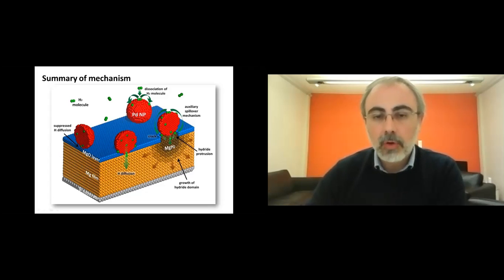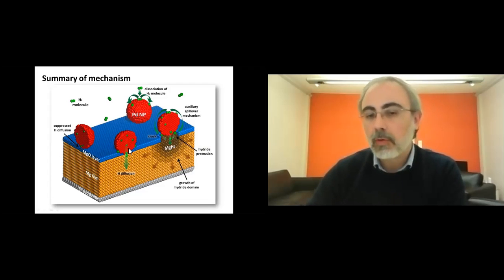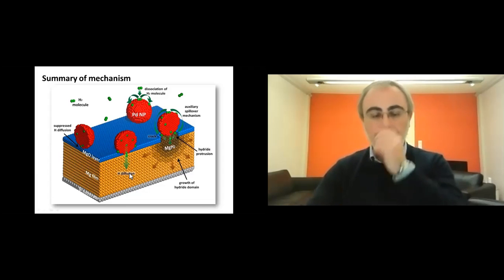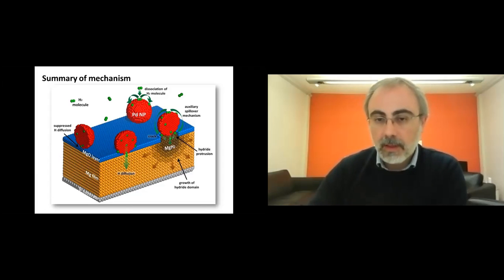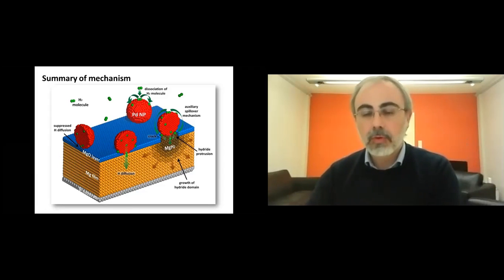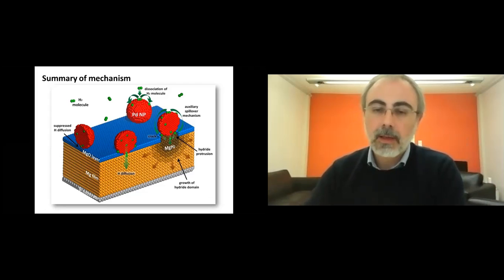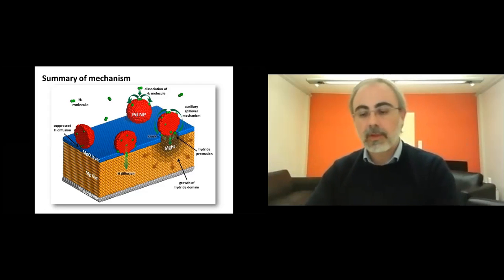If the palladium nanoparticle is deposited before oxidation, then we have created what is called an open nanoportal. So hydrogen atoms can penetrate and diffuse into the underlying magnesium film. And once this happens, the protrusion is created because of the hydride expansion. And of course, there might be an auxiliary spillover mechanism because of this protrusion exposing magnesium hydride film above the surface of the magnesium oxide.